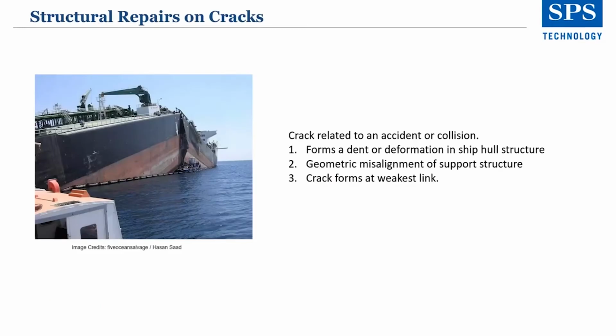Due to their size, for instance, hairline cracks may not be picked up during the construction and addressed. Under normal circumstances, these cracks may not affect the ship structure integrity, but when an unforeseen event takes place, like a collision with another ship, or a grounding event or impact from docking during bad weather conditions, these existing cracks could propagate at a faster rate and lead to structural failure and compromise the integrity of the structure, whether it be the ship's hull or one of the ship's tanks.